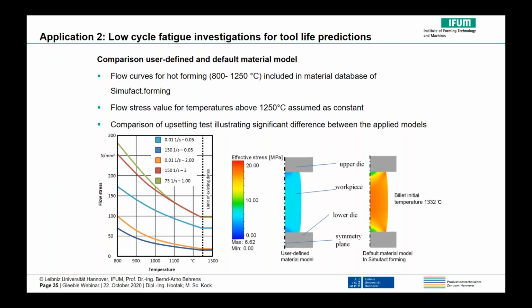We applied the commercial FEA software package Simufact Forming, and one problem is that these FEA software packages have databases where the flow curves for hot forming, for example, are included in the material databases, but only for flow stress values up to temperatures of 1250, for example. So when the temperatures are above this one, then the flow stress is assumed as constant.